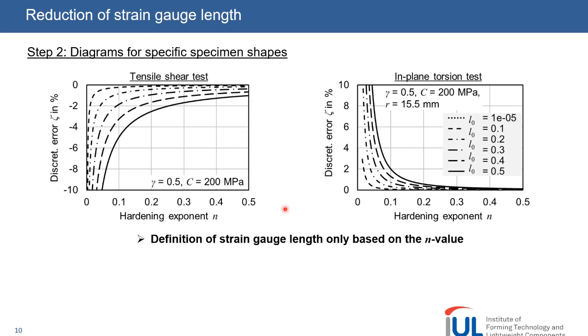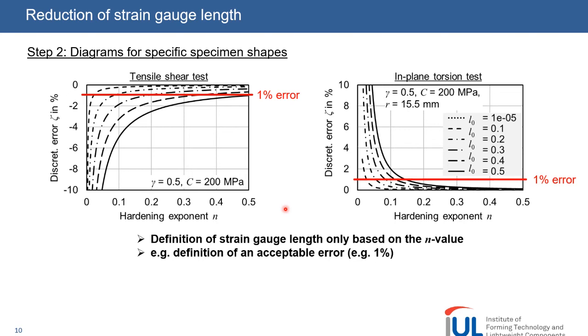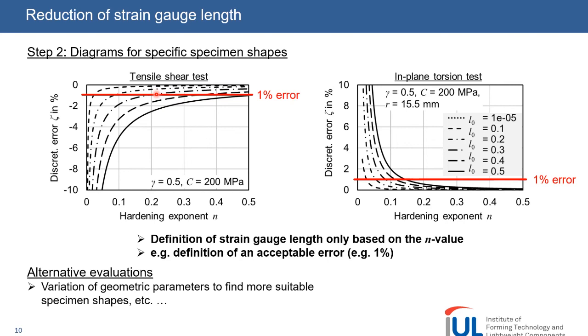But how can we use these diagrams? We can, for example, draw a line of acceptable error and choose proper strain gauge lengths for the DIC setup. For example, a material with a hardening exponent of 0.2 needs a strain gauge length below 0.3 mm for the shear tests of our investigations to stay below 1% discretization error. We can also use the analytical model to find more suitable specimen shapes which are less sensitive to the discretization error.